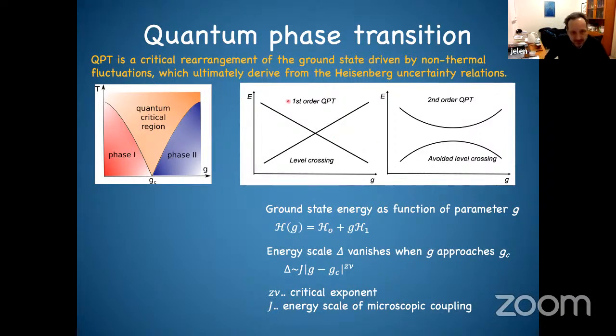And you can distinguish whether it's a first order quantum phase transition or a second order one. Either you have a so-called level crossing, so these two guys don't know each other, or you have what is called avoided level crossing, so you will never close the band gap. It also means that there is no interaction between these two orbitals. Theoretically, you can write the Hamiltonian in some standard form, plus then you have some G factor, which is an extra term. Important is that this extra Hamiltonian is not changing the eigenstates of the system. It's only tuning these eigenstates. The symmetry remains the same.